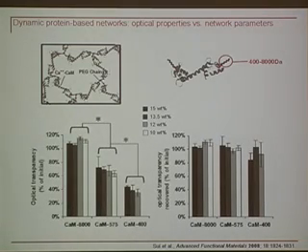And if we vary the molecular weight of the polyethylene glycol units that flank the protein and the total amount of protein that's present in solution during cross-linking, we can vary essentially the extent of this optical shift. So that's what's being shown here. From very little change in optical properties after addition of the ligand to quite substantial changes in optical properties, from say 80% of the initial optical transparency down to about 35% of the initial optical transparency.